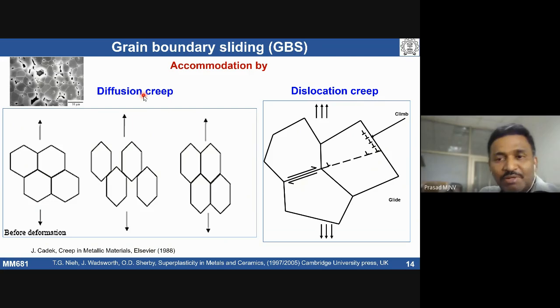But in both the cases, the moment we see grain boundary sliding, if we have a fine grain size of 10 micrometer, you have so many grain boundaries that can lead to grain boundary sliding. Once there is grain boundary sliding, that means there is a strain, and that strain is typically going to be very high. But when the grain boundary sliding happens, there will be a formation of wedge cracks. The formation of wedge cracks can be avoided when there is a simultaneous deformation mechanism, either diffusion creep or a dislocation creep mechanism.